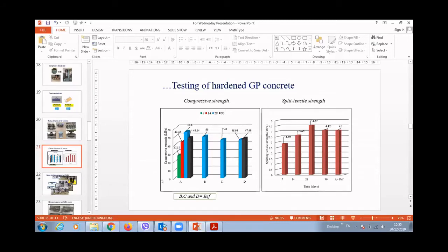So what we found out here is that the compressive strength increased with time after 28 days. Then there is a slight decrease of 8 to 10%. We believe that the decrease in the strength after 90 days could be due to the continuity of the geopolymer reaction with the alkali activator and the binder. Why? Because the chemical reaction and the dissolving process of the raw material by the alkali activator goes faster in the first time, then continues slowly, which is called microreactions. That produces more free molecules of water in the system or in the main matrix. And that, of course, will affect the strength with time.